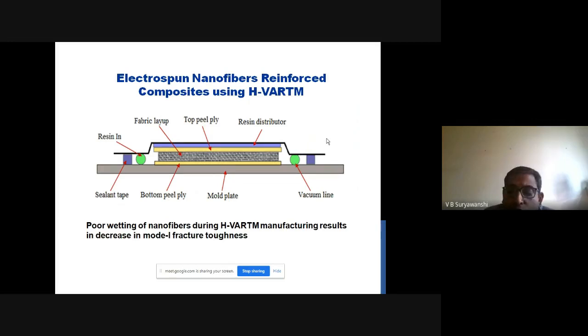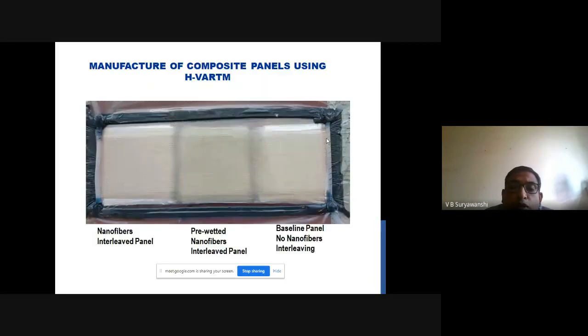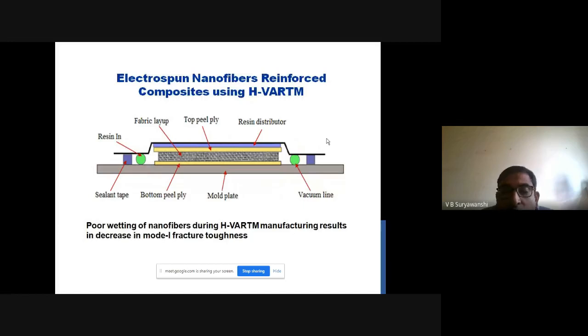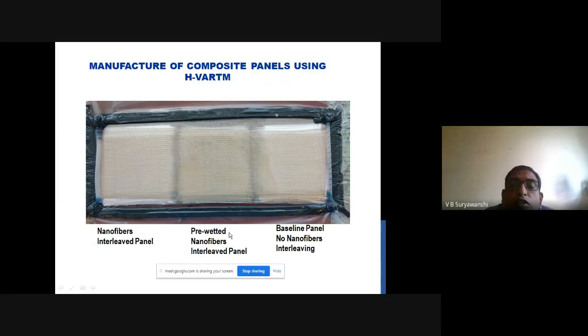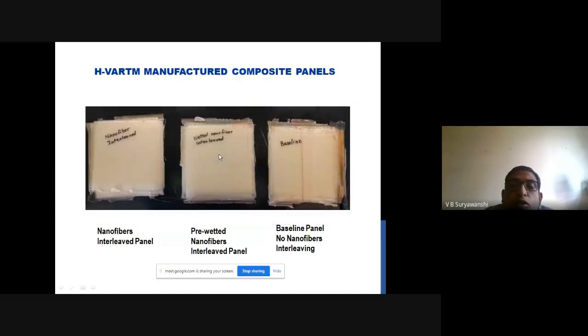Lastly, what we saw is when you put those dry electrospun fibers in between the two layers, there is no proper wetting of the nanofibers. So how to solve this problem? What we had done is we had applied pre-wetting. Pre-wetting means this nanofiber mat was soaked in the resin, and that improves the resin infusion, and that helps in improving the performance.